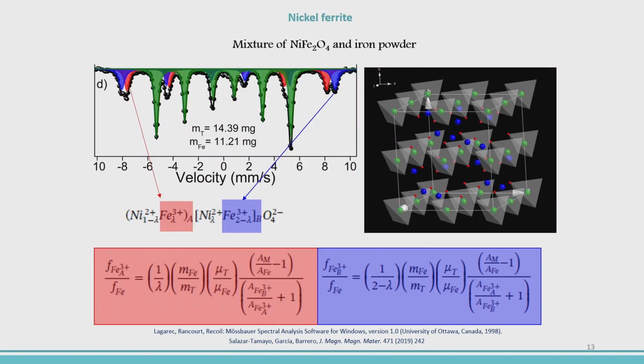The mass of the reference materials is from the ferrite. I work within these two. The amount is arbitrary. You can choose any value. What we did, for example, we mix 200 milligrams: 120 milligrams is ferrite, and the rest, 80 milligrams, is iron. We mix fully, and then we can take from this mixture a small amount in such a way that we are in the range. This is one method, or you can just mix whatever amount. And the second thing is that we perform thickness correction by software.